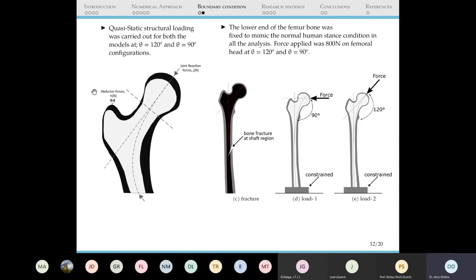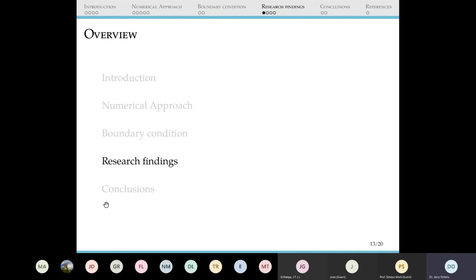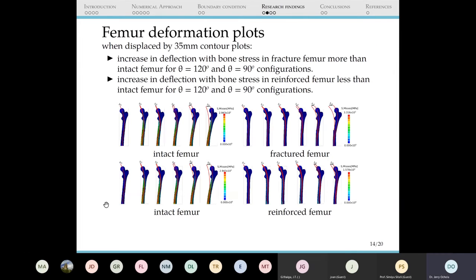Our findings are that when we applied a load that displaced the bone by 35 millimeters, there was a lot of deflection in the bone in this single stance configuration, as opposed to when the force was applied at 90 degrees. This happened in the intact bone, and also in the fractured bone.